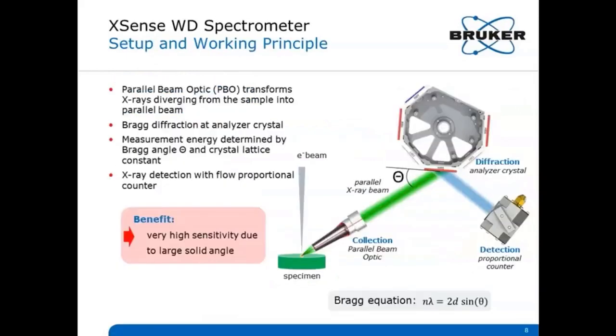This slide here shows the setup and working principle of the X-sense spectrometer. The parallel beam optic is positioned pretty close to the sample, and thus captures a large effective solid angle. So we've seen the optic, which is a very important part in this parallel beam spectrometer, is close to the sample, so we capture X-rays with a high effective solid angle.